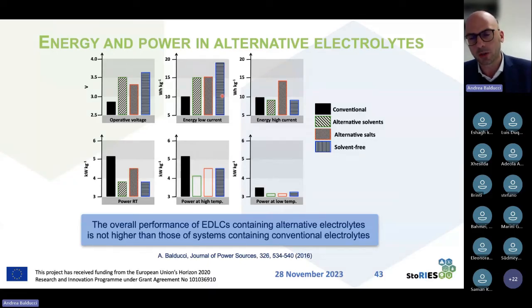But what is important to outline here is that when we are using a supercapacitor, as we said before, we don't want to apply low current. That means we don't want to use this system in hours, because this is not convenient. We would use a lithium-ion battery. So what we want to do is to use this system in a time frame of minutes or seconds. And to do this, we need to apply high current.